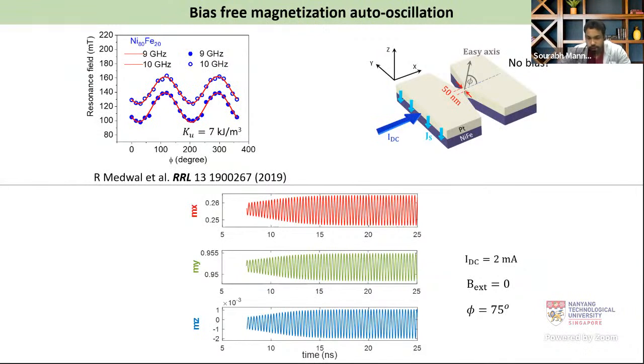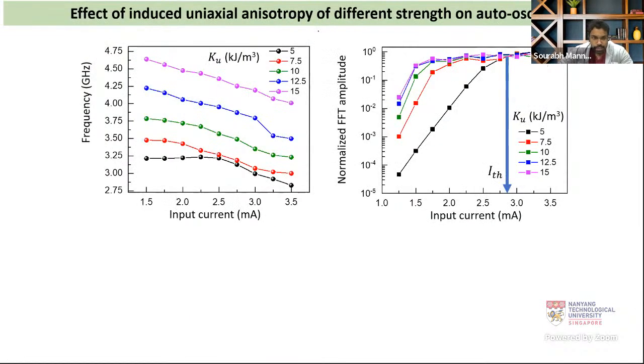Now the question is, what is the anisotropy energy constant? Ku is the uniaxial anisotropy constant, which can also be termed as the anisotropy energy per unit volume. So to study the role of this Ku, or to see what is the optimum value of this Ku, we studied the Ku dependent behavior. As you can see in this left graph, if we increase Ku, the oscillation frequency changes. So we can say that with this anisotropy energy, we can actually tune the auto oscillation frequency of the spin Hall nano oscillator.